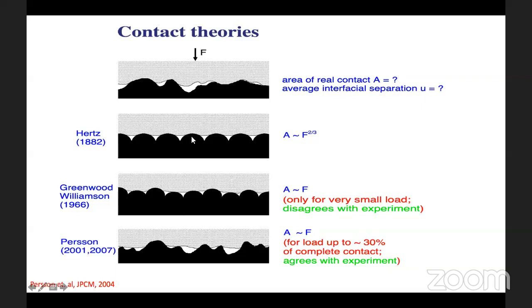The Hertz model does not agree with experiments, because in experiments we see that the area of real contact is proportional to the normal force. This is Coulomb's law. But Hertz says that the area of real contact depends non-linearly on the force, which is obviously not right.